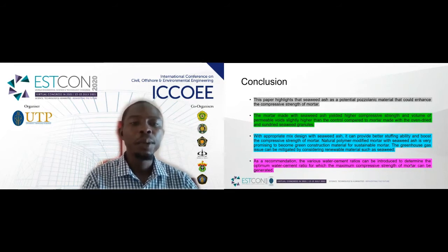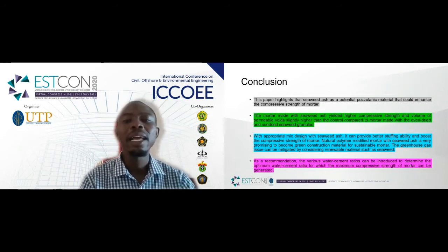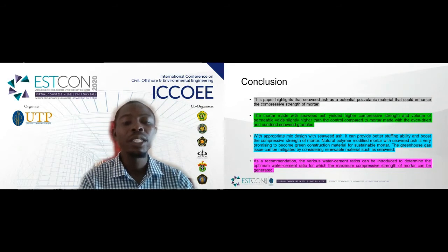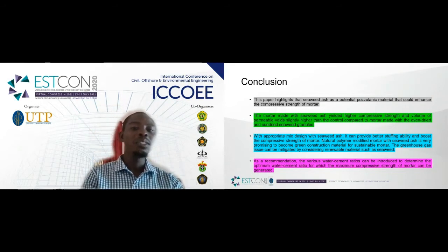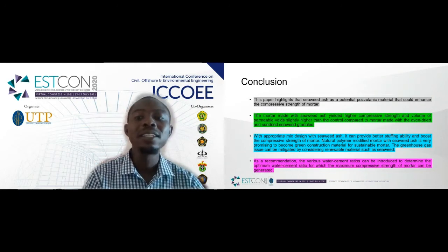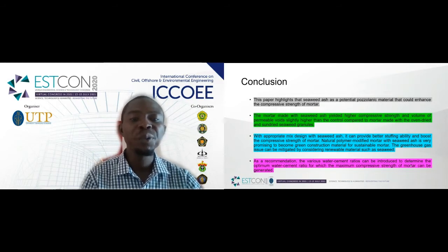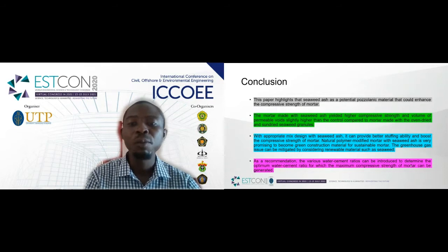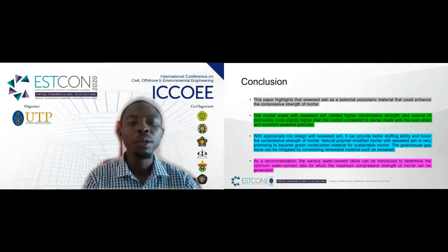Conclusion. This paper reports the importance of seaweed ash, its utilization as a potential pozzolanic material that could enhance the compressive strength of mortar. The mortar made with seaweed ash yielded higher compressive strength and volume of permeable voids slightly higher than the control compared to mortar made with the oven-dried and sun-dried seaweed granules. With the appropriate mix design, seaweed ash can provide better stuffing ability and boost the compressive strength of mortar. Natural polymer modified mortar with seaweed ash is very promising to become green construction material for sustainable mortar.